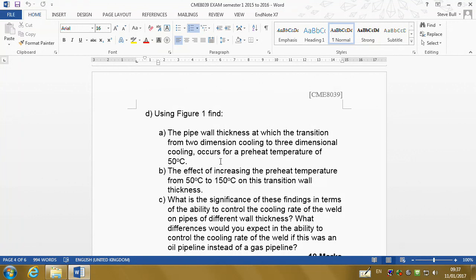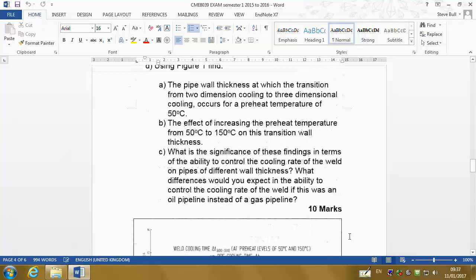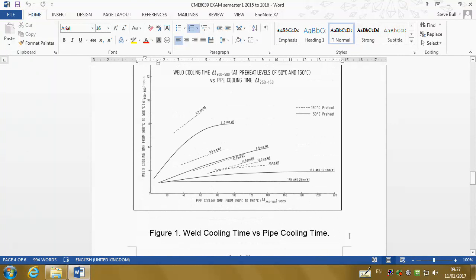And also, this shows up in this figure. And what it shows up for, if you look at something which is very thick, like here, thick pipe, 25 millimetres, that curve is flat. If you look at the thin pipe, it goes up, starts to flatten off at the end. So this one we know is definitely three-dimensional. This one we think is two-dimensional. So just by knowing that, you can then identify the curve in between those where it goes from this sort of behaviour to this sort of behaviour.